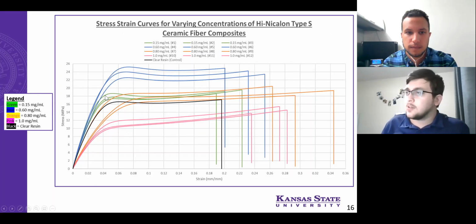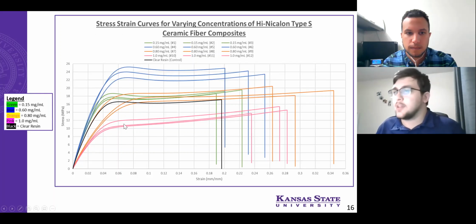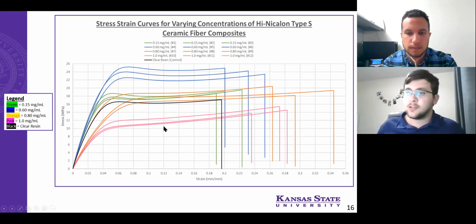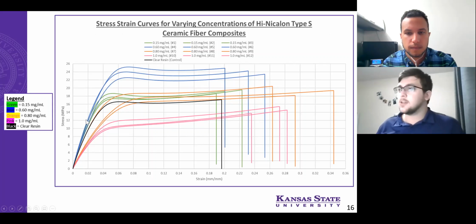The green here is 0.15 milligrams per milliliter. The blue is 0.6 milligrams per milliliter. The orange is 0.8 milligrams per milliliter. And this pink down here is 1 milligram per milliliter. And then the black is just a neat resin sample. So you can see here the 0.6 milligrams per milliliter really outperformed the other concentrations that were tested in the form of elastic modulus as well as its fracture strength.